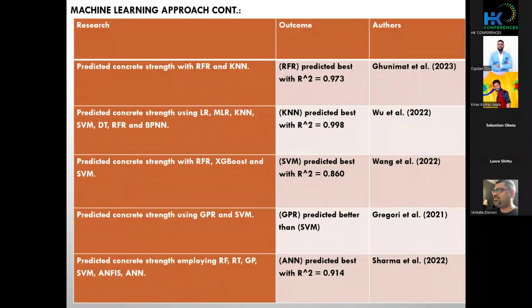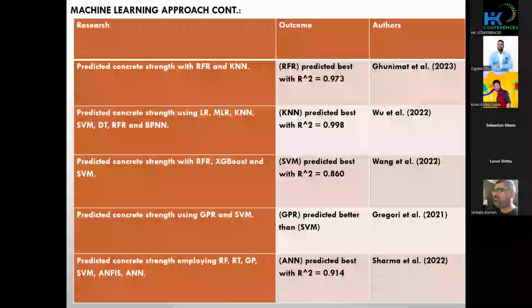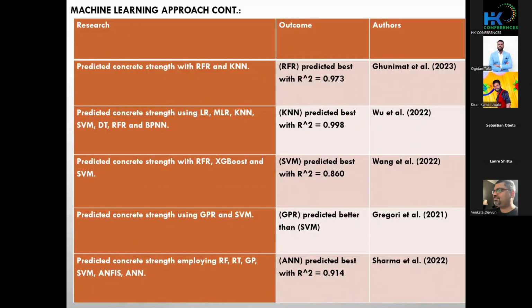And secondly, an experiment performed by Wu et al. They predicted strength of concrete as well, but this time around using the logistic regression, multiple linear regression, k-nearest neighbor, support vector machine, decision tree, random forest regression, and also backpropagation neural network. In this case, it was observed that k-nearest neighbor predicted best with correlation coefficient of 0.998, followed by the third experiment by Wang et al. They predicted the compressive strength of concrete containing ground granulated blast furnace slag using random forest regression as well, extreme gradient boosting, and support vector machine. They observed that support vector machine predicted best with R square equals 0.86.